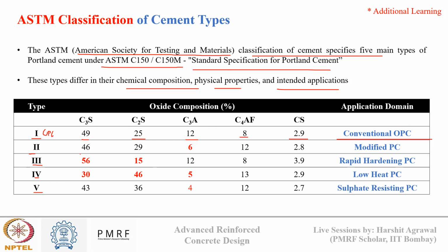In type 2 cement, compared to type 1 cement, we see major changes in the quantity of C3A, which is reduced from 12% to 6%. So if there is less C3A, the threat of sulfate attack will be reduced. So earlier, if you remember in our discussion, we saw C3A reacts with gypsum to form ettringite. If there is more amount of C3A in the system, ettringite converts into monosulfate, and externally when sulfates come into concrete, monosulfate can again convert back to ettringite, which can cause cracking in concrete. So if initially C3A proportioning is less, that ettringite to monosulfate conversion will be low. So delayed ettringite formation chances will also be lower. So sulfate attack chances will be lower.